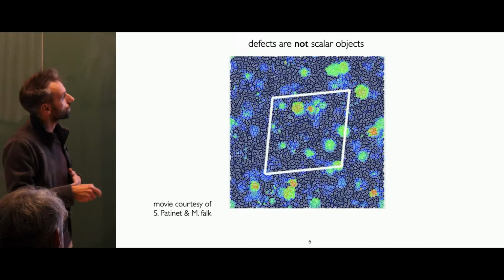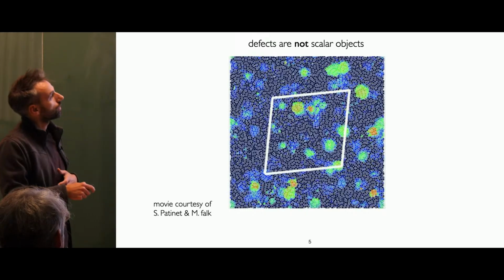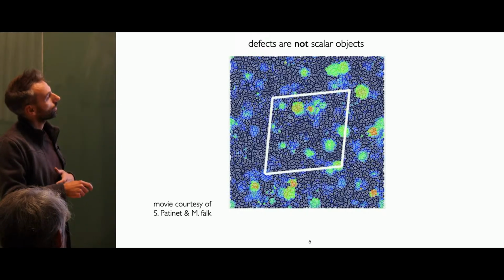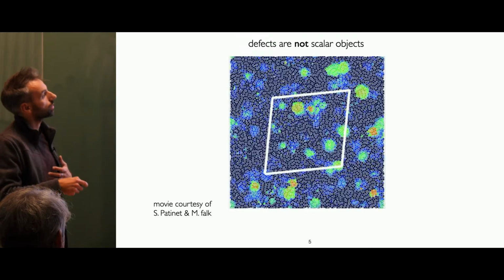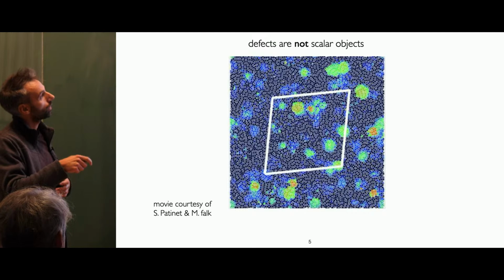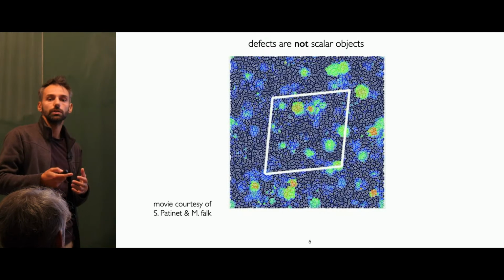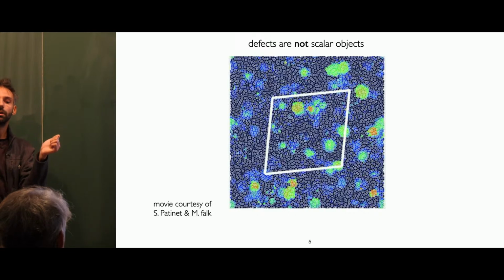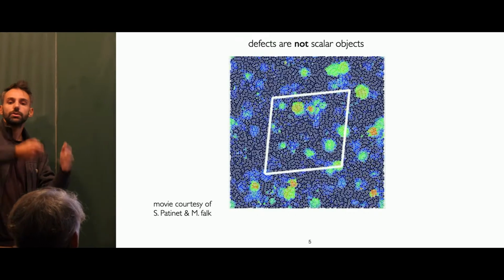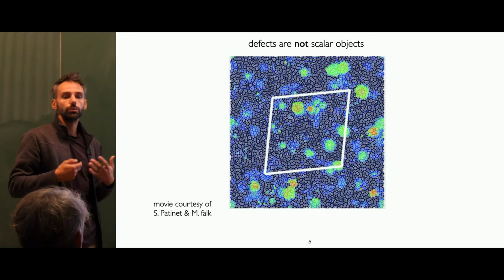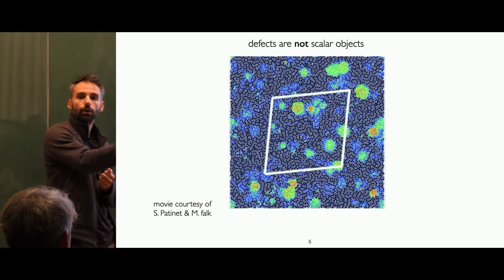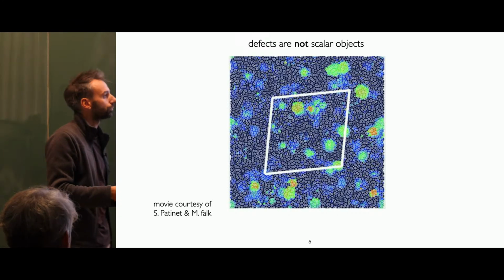But generally, what you see is that in a glass you have weak regions and other regions that are more strong. So for example, this is the local yield stress in a given geometry. The orange and yellow colors show you regions that have small local yield stress. So it's a region where I shear just a little bit and the system will already yield. And in blue, there are regions that are very strong. I could deform it for a very long time and I will not see any plasticity.